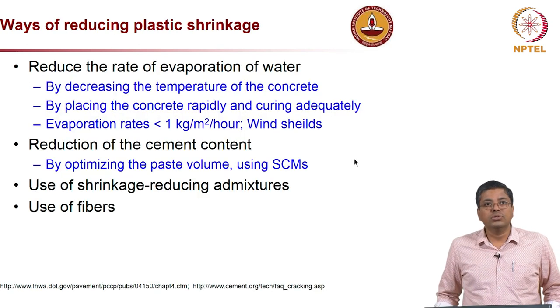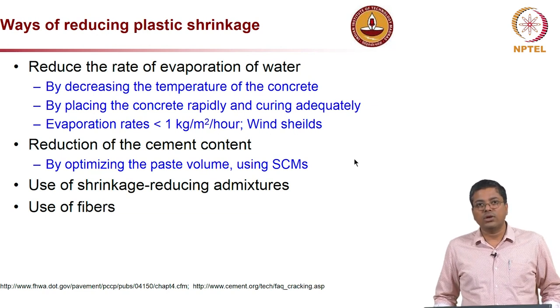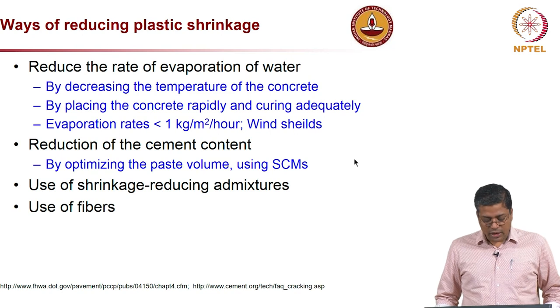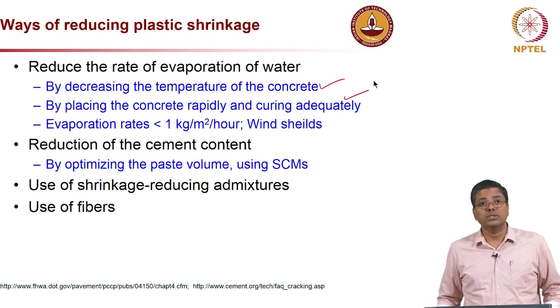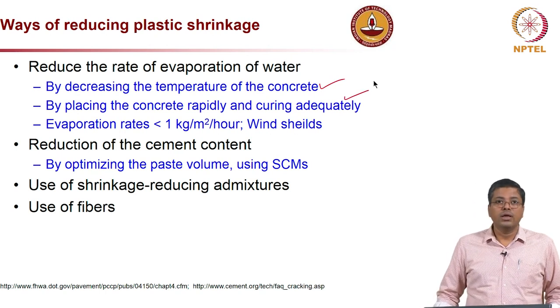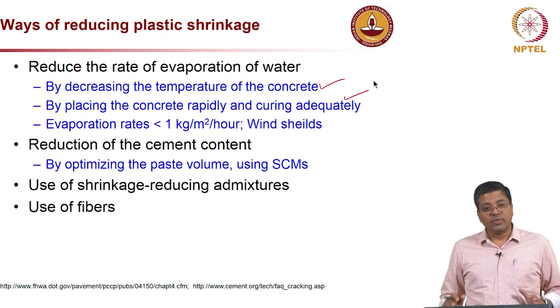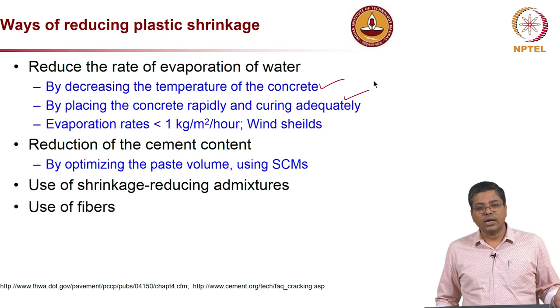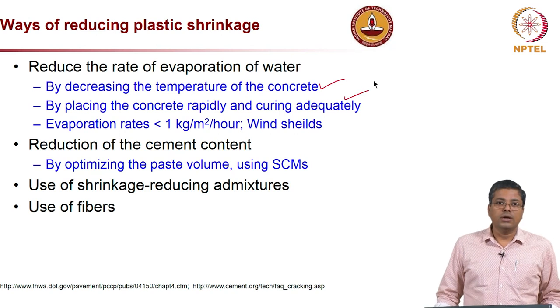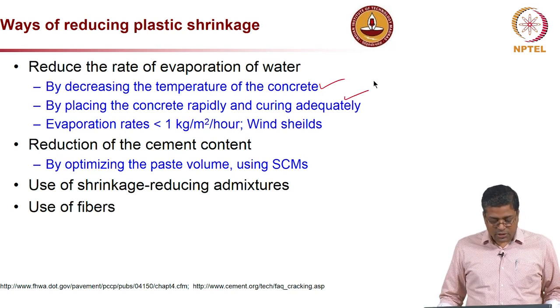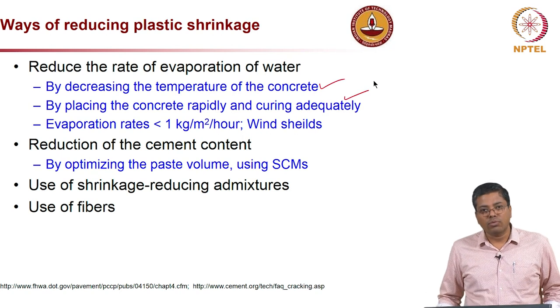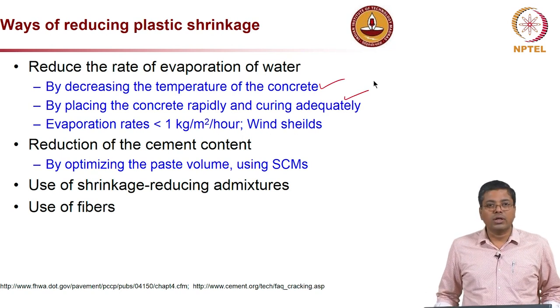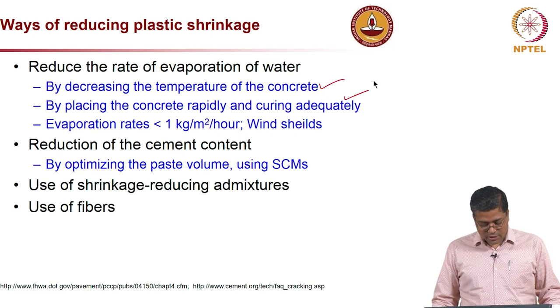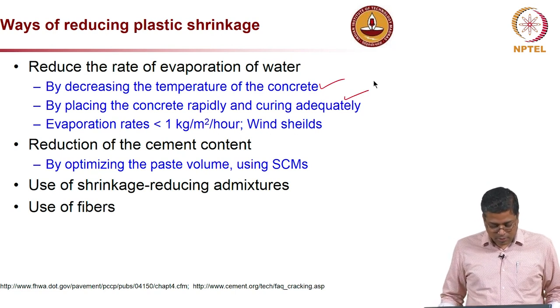Now, how do we reduce plastic shrinkage? The first thing is we have to reduce the rate of evaporation of water. How can we do that? By decreasing the temperature of the concrete, or by placing concrete as soon as it is mixed and providing adequate curing. And if there are wind conditions, we have to ensure that the air movement right above the concrete surface is less, because if you have more air movement, it will carry more and more moisture from the concrete, which will eventually lead to fast drying, which is not recommended.